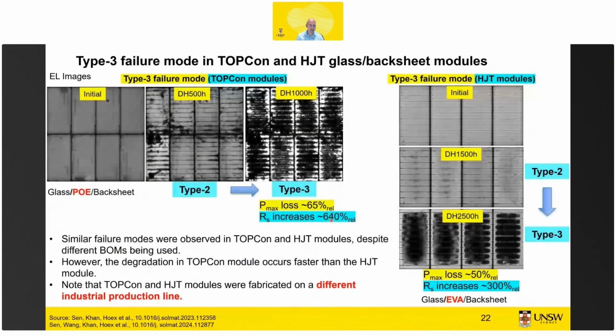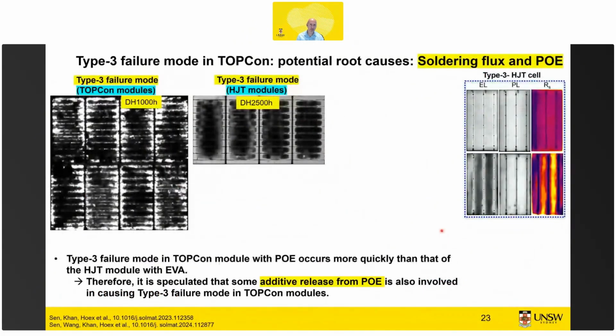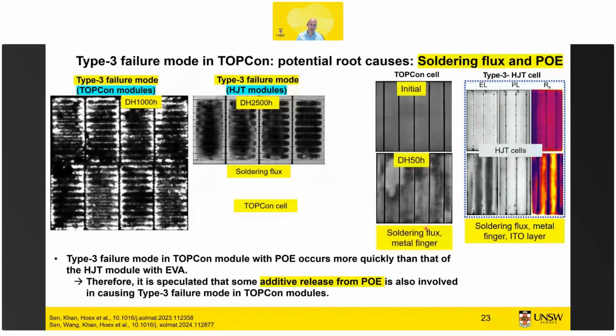So if we... the comparison that we show here is that it looks very similar to heterojunction. However, if we look at the root cause, for heterojunction, we identified that it was mainly related to soldering flux and its strong reaction with TCO. That was the conclusion we came to at that point.